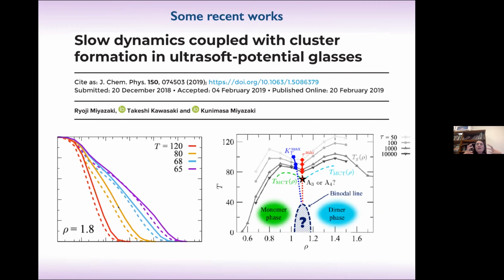And in these particular models, this kind of ultra-soft potentials, you can form clusters, and the particles can overlap with each other. In particular, in the simulation work of Miyazaki, they saw that there was a region in the phase diagram where you go from a prevalence of monomers to a prevalence of dimers. And in between these two phases, monomers and dimers, they find this logarithmic dependence of the density correlators. And so they put in their paper, is it an A3 or an A4? That's very interesting, and it would be good to check.